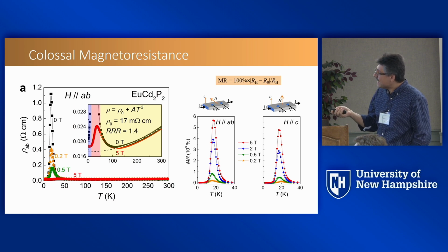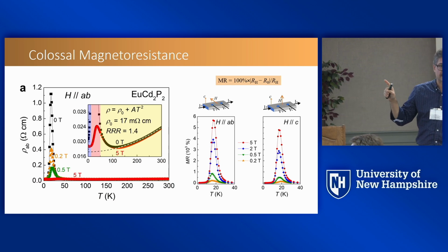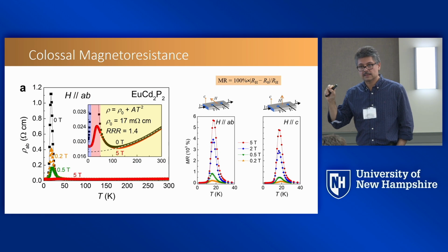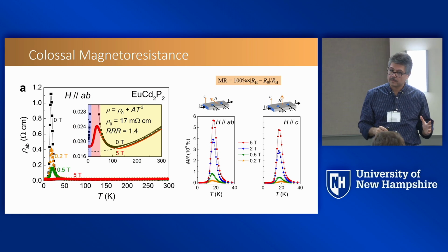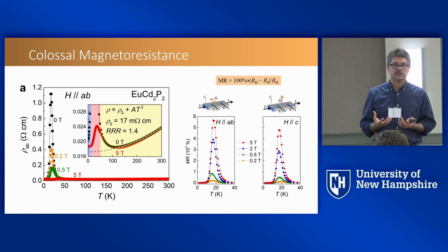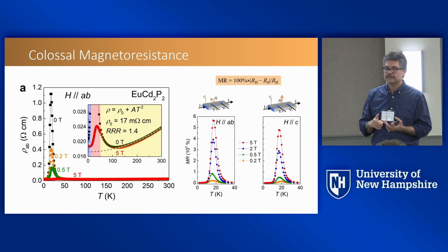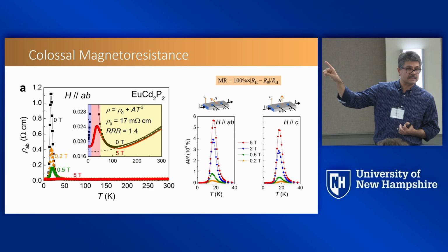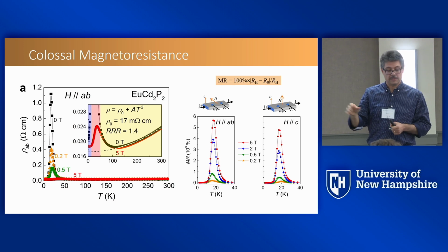If you look at this negative magnetoresistance, it reaches 10 to the 3 percent, which is larger than colossal magnetoresistance in single crystals of manganites. Colossal magnetoresistance is actually a very well-known phenomenon. During the '80s and '90s, everybody studied them. But this phenomenon was understood in terms of double exchange interactions and Jahn-Teller distortions in correlated oxide materials. This system does not have mixed valency or double exchange interactions. It does not have Jahn-Teller distortions.